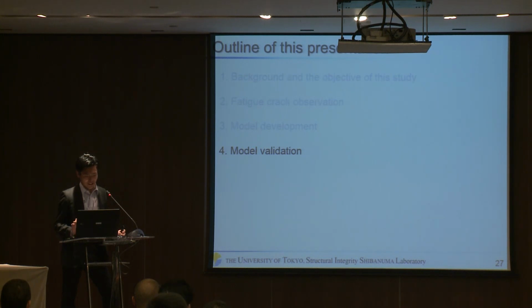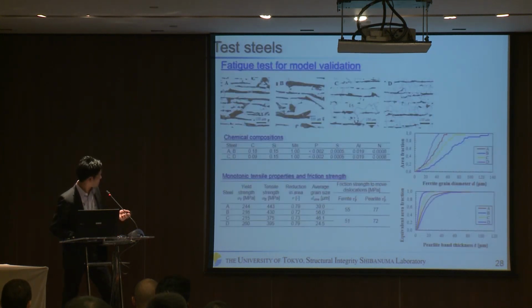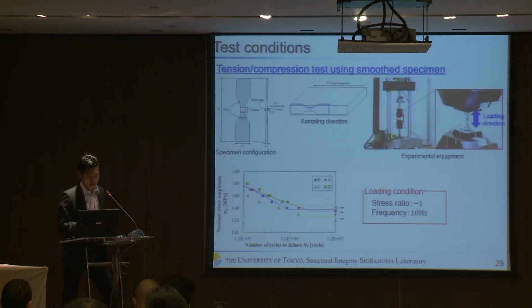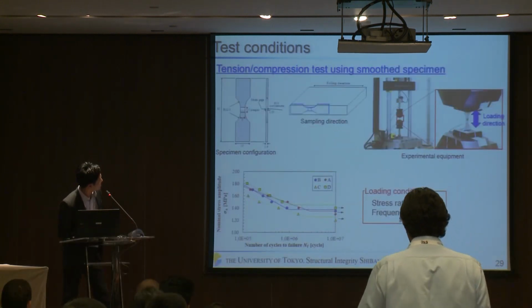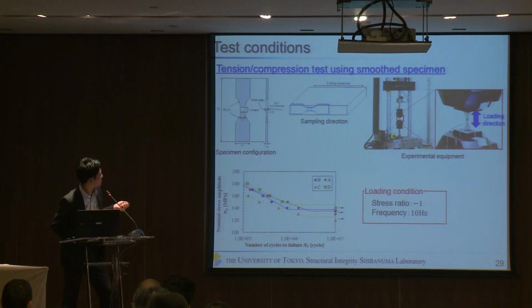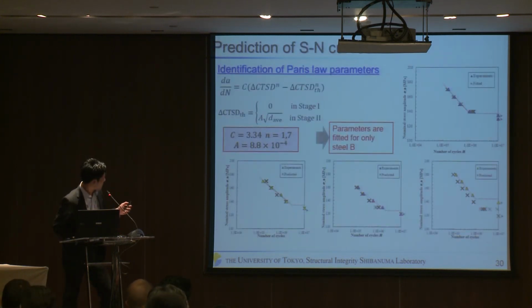Let's move on to the model validation. In this model, these different steels are used, and compression tests were conducted using smooth specimens. This is the same one as that of the observation, and fatigue life curves were obtained, along with prediction of S-N curves. The Paris law parameters are fitted for only steel B. So this is fitted, and with these parameters, these predictions are obtained. And as you can see, it's quite good agreement.